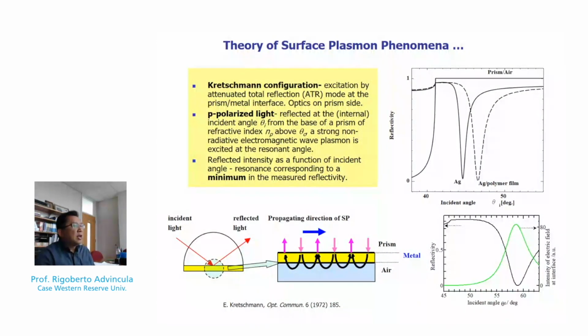So as shown here, you have a prism and air surface. The reflectivity goes to a maximum at a particular angle and then becomes flat. That is the case of a prism without gold. But if you attach a gold surface on top of the prism made of glass, as you reach the critical angle, the reflectivity will start decreasing. Let's say in this case for silver metal, okay? So that dip is a very sensitive phenomenon that relates to the dielectric medium.